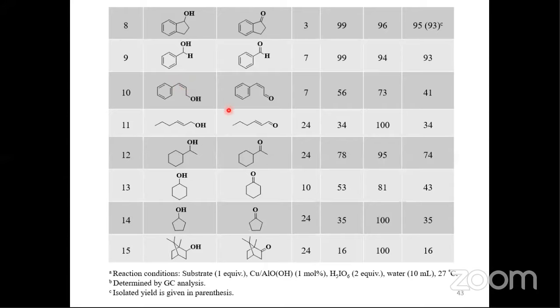But if you look at, in this case, only the alcohol is oxidized. Now the double bond is unaltered during the course of the reaction. That is the selectivity, right? So the cinnamaldehyde is obtained in a moderate yield, not very good, but the selectivity is good. The selectivity is 73%. But here in this case, even the selectivity is 100%. It means only alcohol is oxidized. In this case, of course, a trace amount of epoxide is also observed, but here only the alcohol is oxidized, the double bond is not at all oxidized, so selectivity is 100%.